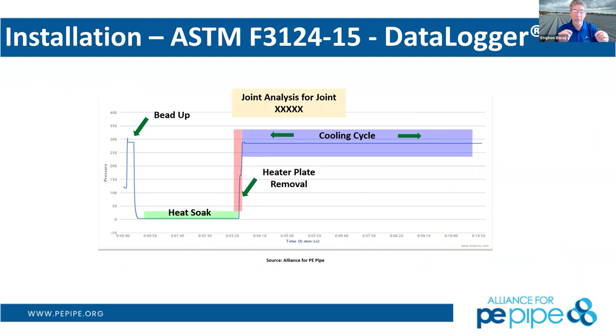Once you see that melt bead first coming up, then you can reduce the interfacial pressure of holding those ends together, and you want no interfacial pressure during that heat soak. Now you're just putting all that heat into the polyethylene and melting it back to a certain point, several thousandths of an inch back in there over this whole heat soak time, which is, again, a known value for the size of pipe that you're using. You're going to remove the heater plate. You're going to bring those molten ends back together now with a known and controlled interfacial fusion pressure. And that's going to be this part here.